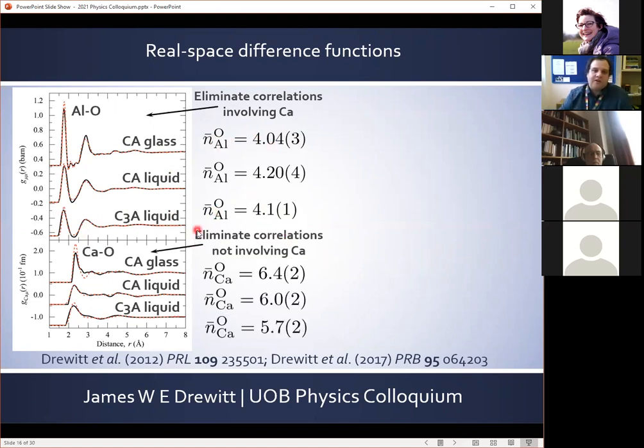Similarly, we can combine the measured structure factors to eliminate all those correlations which don't involve calcium. And so here the aluminium oxygen peak disappears, and our first peak arises from our calcium oxygen nearest neighbor bond length. And again, we can integrate over this peak and obtain very reliable values for the average calcium oxygen coordination numbers, which are around 6.